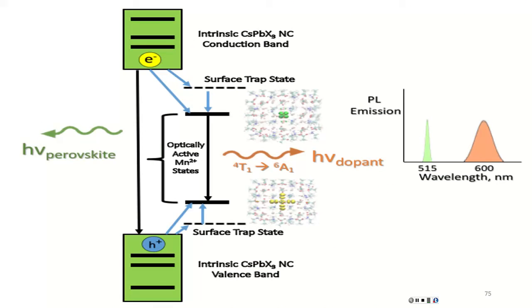Okay, and here is an idea of why one would put doping into a perovskite quantum dot. As we already discussed, and everyone in this audience knows, the ability of a material to emit depends on the skills of the chemist who cooks your quantum dots, on the presence or absence of ligands on the surface. And sometimes ligands may desorb. One can choose wrong ligands, or it can be a not ideal surface. So it's expected that the quantum dot is emitting, but sometimes there are surface traps.